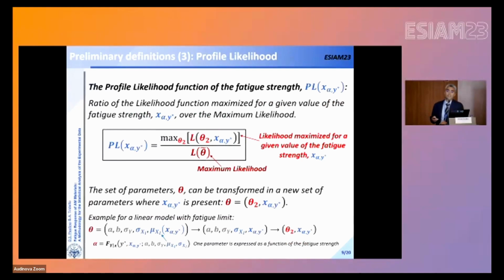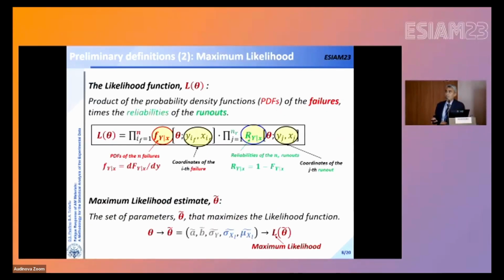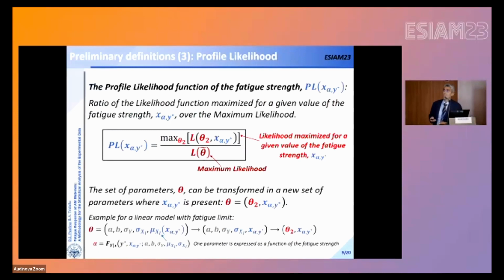The way in which we can take it into account, according to well-known statistical procedures, is through the profile likelihood. I don't want to use too much time in defining it, but it's just a ratio between two maximum likelihoods. On the bottom, the maximum likelihood that you have got with the estimates from the maximum likelihood principle. On the top of the ratio, it's a particular maximum likelihood that depends on a fatigue strength value. To get this top value, you have to transform the set of parameters defined in the model so that the fatigue strength appears in the set of parameters.